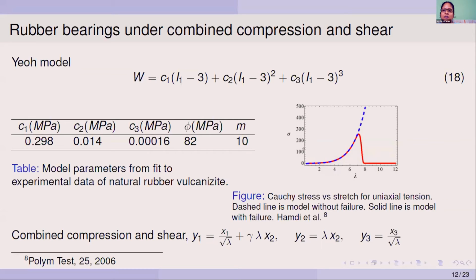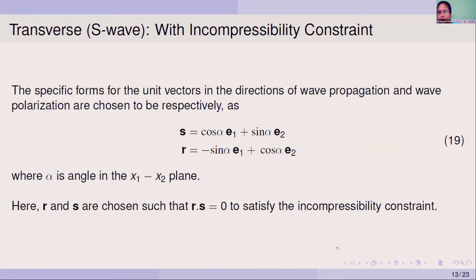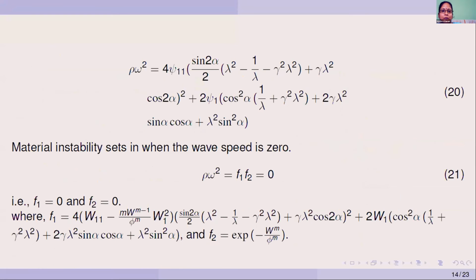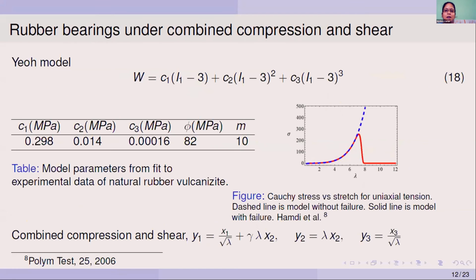So this figure shows the Cauchy stress versus stretch response. This blue dashed line is the model without failure. This is for the intact material behavior. And this red solid line shows the model with failure. And this is the equation of combined compression and shear for an incompressible material. Here gamma is the amount of shear strain, and lambda is the amount of compressive stretch.